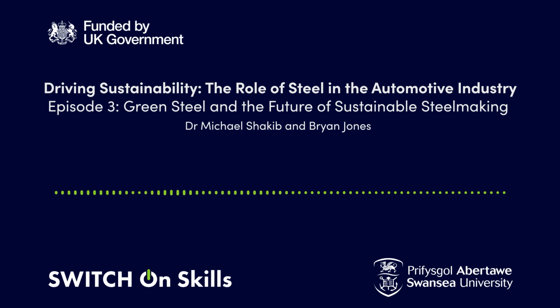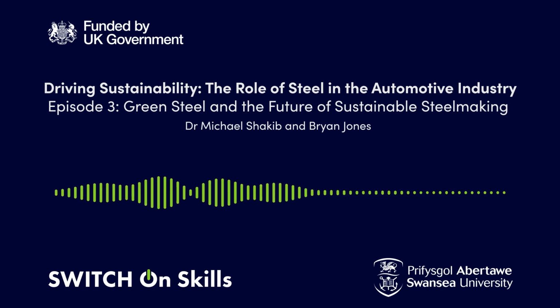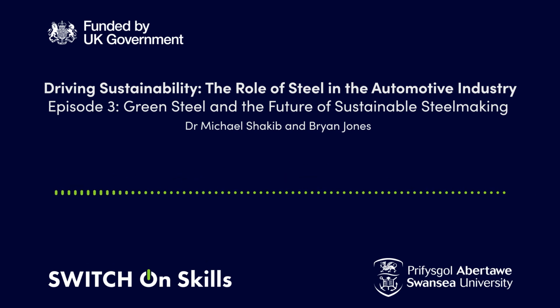So you start off with a ladle of steel, and from this ladle there's a progressive transfer of the material to a vacuum system which is attached to the ladle, and by flowing steel continuously from the ladle, so that each ton of steel progresses into this vacuum area over a period of time, it's possible to reduce carbon levels, as I said, typically from BOS plant operations of 0.04 to 0.05% to 0.003, 0.004% carbon and nitrogen, as well as getting rid of other elements as well.